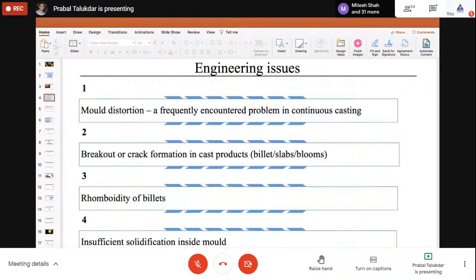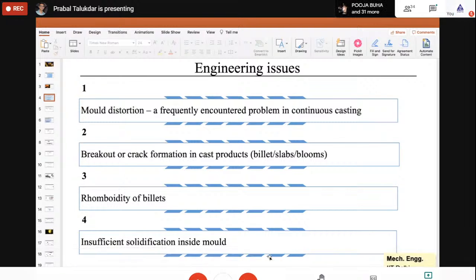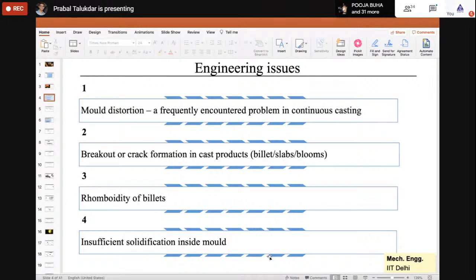These are the engineering issues which happen with the continuous casting process. The first one is the distortion of the mold. The mold is that rectangular channel which I have been mentioning, which gives you the shape of the solidified steel. Although it is made of copper, because it is exposed to very high temperature molten steel, it also gets different stresses, including thermal stresses, and because of that, the mold distorts after a certain period of time. It may work for 1 month, 2 months, 1 year, but over a period of time, the mold might distort.